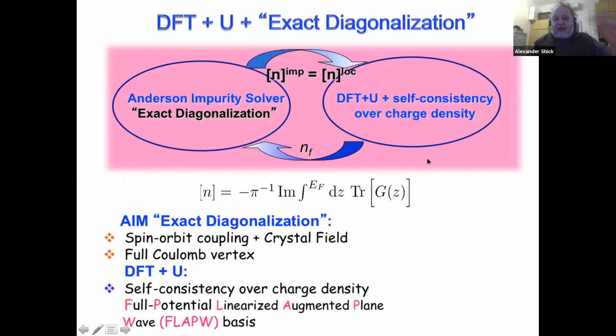Let me say maybe a couple of words about our method. The difference between the conventional LDA plus U and our extension is that we do not calculate the occupation matrix inside of the DFT plus U, which would correspond to the single determinant approximation. Instead, we obtain the parameters from DFT or LDA plus U and solve the Anderson impurity model with these parameters and calculate there the occupation matrix. And then we put it back into the LDA plus U, and we do it self-consistently. And indeed, we include the spin orbit coupling, the crystal field, the full interacting matrix, and we use the accurate full potential LAPW method.